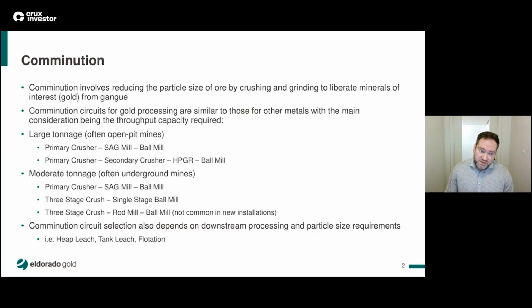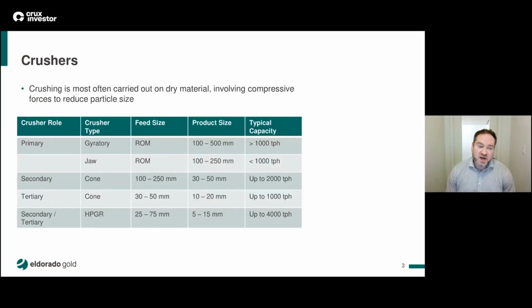Smaller tonnage mines, often underground mines, can also use primary crusher, SAG mill, ball mill circuits, or three-stage crush followed by single-stage ball milling, and in some cases previously, rod mill, ball mill circuits were quite common. The circuit selection also depends on the downstream processing and particle size requirements, i.e. heap leach, tank leach, or flotation, which all have different requirements. Crushing is most often carried out on dry material, involving compressive forces to reduce the particle size of the rocks being fed to the crusher.